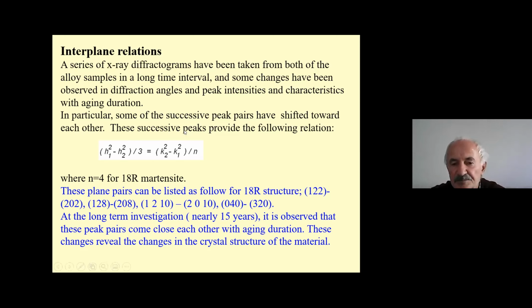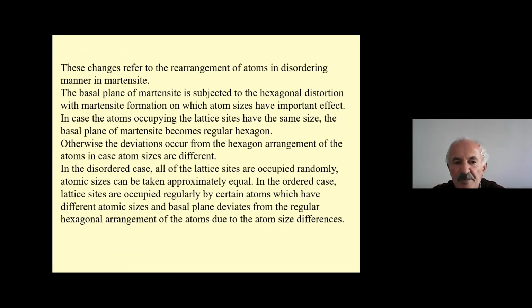These successive peaks provide the following relation for 18R martensitic structures. Also, this plane pair can be listed as follows for 18R structures: 122, 202, 128, 208, 1 2 10, 2 0 10, 040, 320, and others. At the long-term investigation, it is observed that these peak pairs come close to each other with age and duration, and this change refers to the changes in the crystal structure of the material.